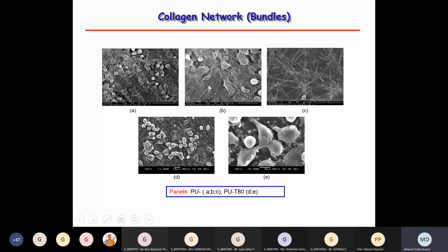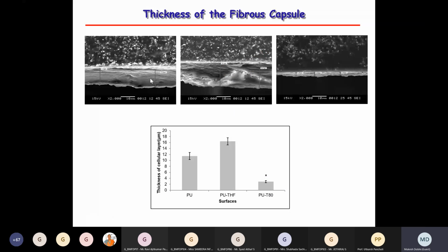Then collagen network. Look at how the collagen network has formed. The bundles of collagen. That is the top figure, the top 3 scanning electron pictures, with the unmodified surface, whereas the modified surface you can see at the bottom. So there is a lot of inflammatory activity happening. You can see the collagens here on the top one. Fibrous capsule. The implant is completely covered with fibrous material, so it forms like a capsule. When we have the unmodified polymer, you can see a very thick fibrous capsule is formed around the implant, whereas you don't see that sort of thing happening when you use a modified surface. That's on the right hand side picture actually.